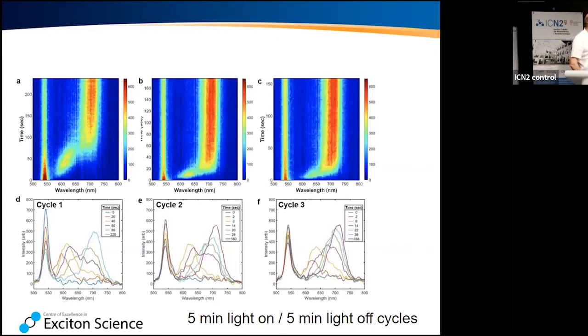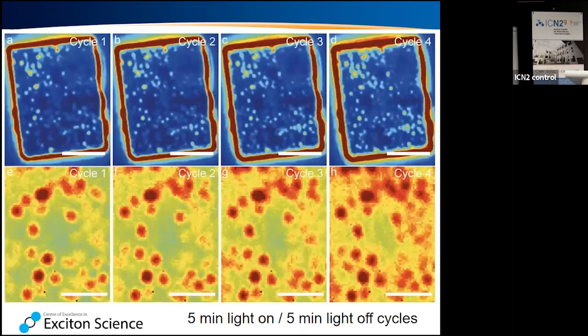And we can do that. We can let the crystal recover again in the dark, and we do it again and again, and it happens over and over. And something that was interesting for us to see is also that once you form a halide-rich domain somewhere, you let it relax in the dark, it goes completely back to fully mixed. And then you do the halide segregation again by shining light on it. You look at this one here, it appears in all the images, in the first cycle, second cycle, third cycle. And then there are others that were kind of weak before or not there at all. And then they get stronger and stronger as you go from first cycle, second cycle to third cycle.